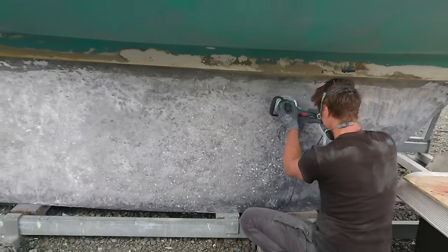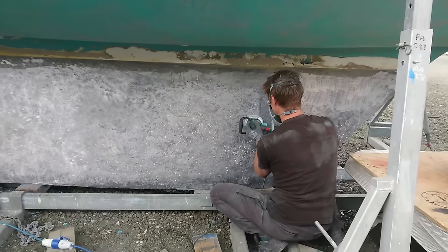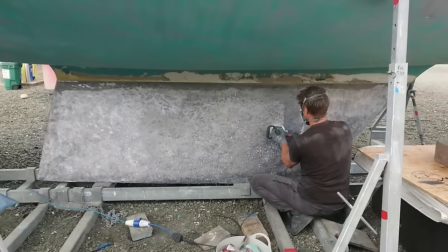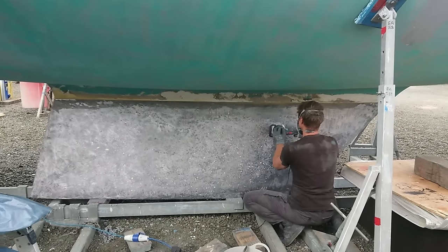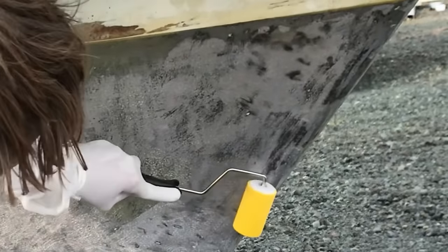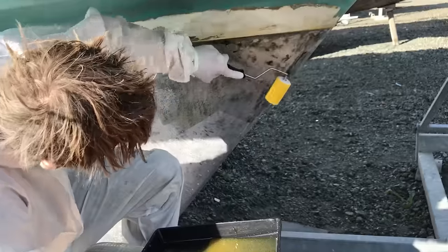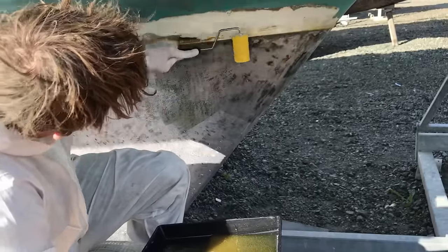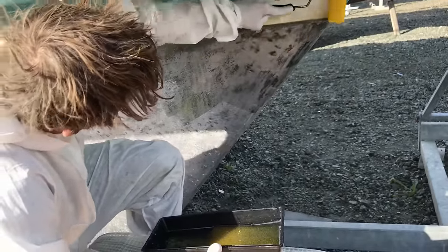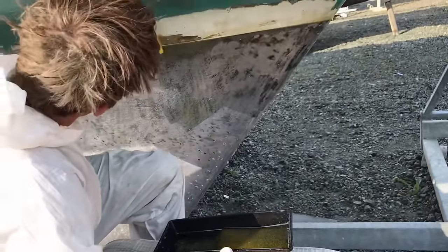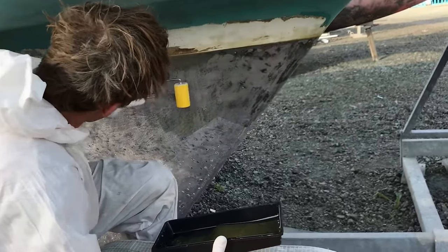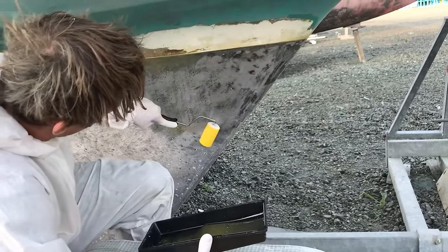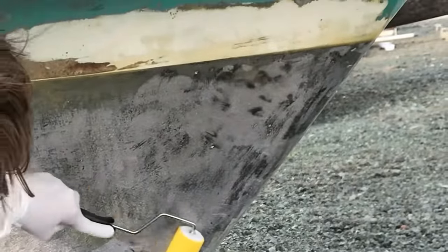Although the keel's solid lead and it doesn't rust, lead does oxidise very quickly, and that layer of oxidisation will form a loose layer and potentially cause anything we put over the top of it to not bond properly and flake off. So I'm getting this done today before it has time to react. The epoxy resin that I'm using here is another West System product called G-Flex, and it's a slightly more flexible and elastic version of their epoxy, and it's what they recommend for applying directly to bare metal before fairing.